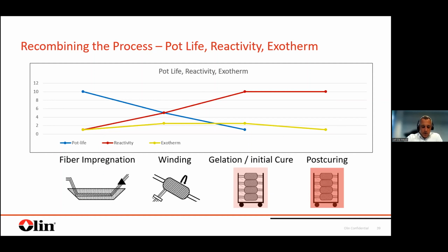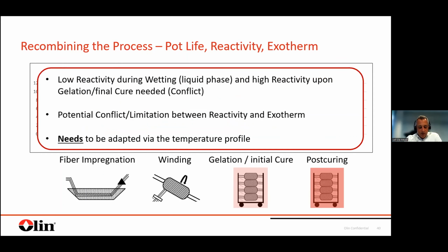Overall, it still makes kind of sense. Reactivity low in the beginning and increasing over time. So this is something that can be managed. So the process requires low reactivity during wetting, high reactivity in the final cure, and in the end, very high reactivity in the post cure, which is not easy to achieve chemically. There are methods to use, for example, some catalysts.